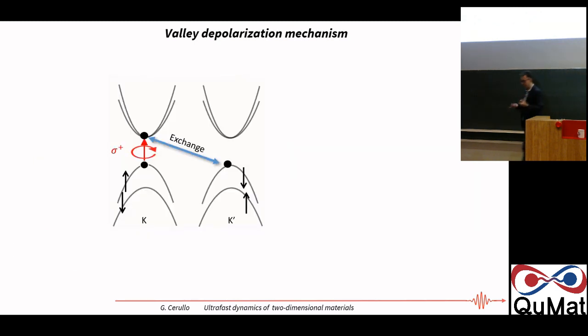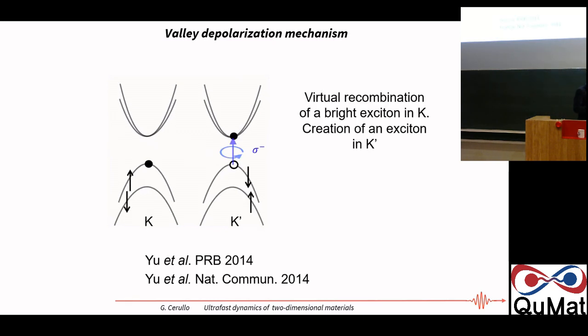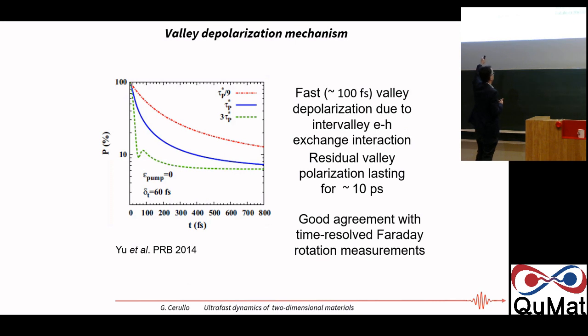So what is the valley depolarization mechanism? Here we didn't really make a one-to-one comparison of our experimental data with theory, but if you look at the theory, you see that there is this so-called exchange mechanism, which is a virtual recombination of a bright exciton in K and the creation of an exciton in K prime. Now, this is supposed to be a very efficient mechanism. And indeed, according to the parameters, they predict a very fast valley depolarization due to this inter-valley electron exchange interaction on the order of 100 femtoseconds. And then there is a slower decay on the order of a few picoseconds. So in very good agreement with what we observe experimentally.